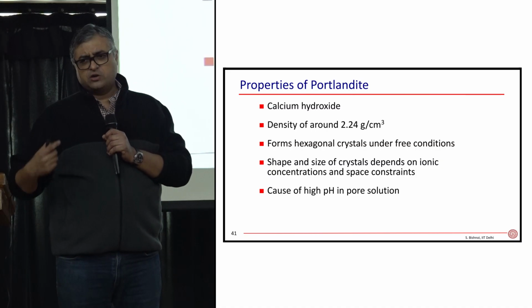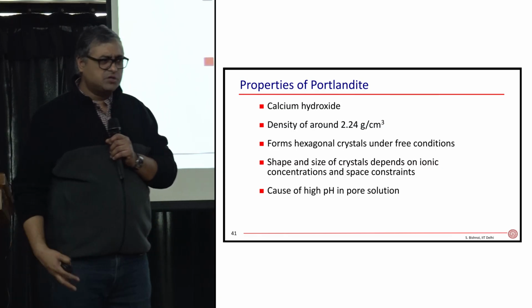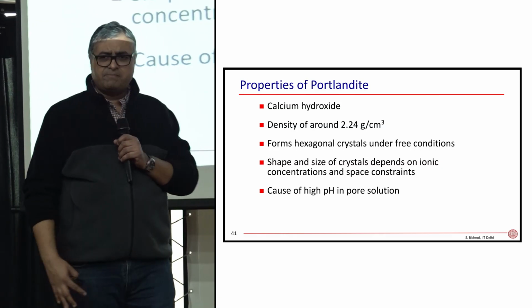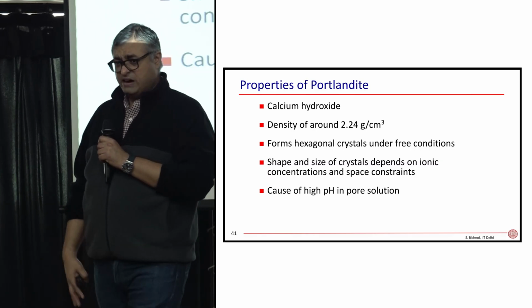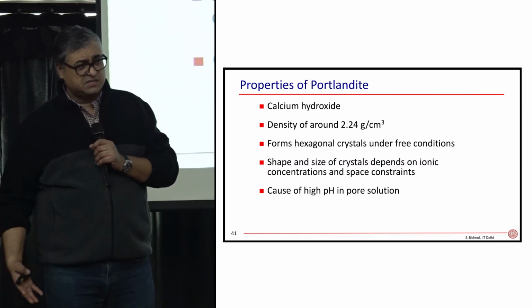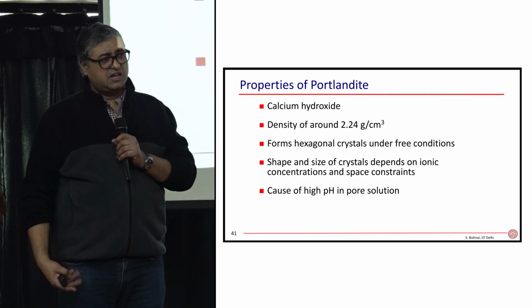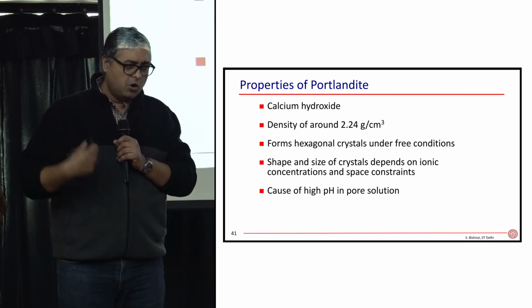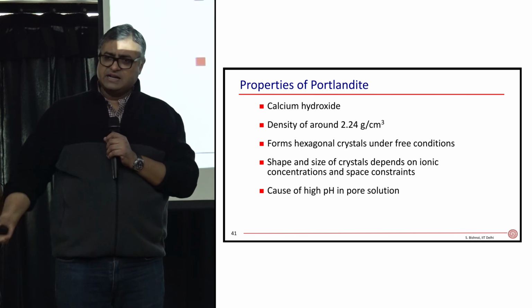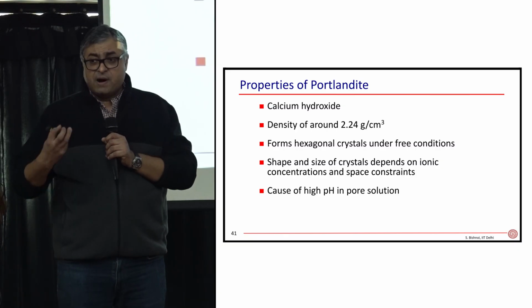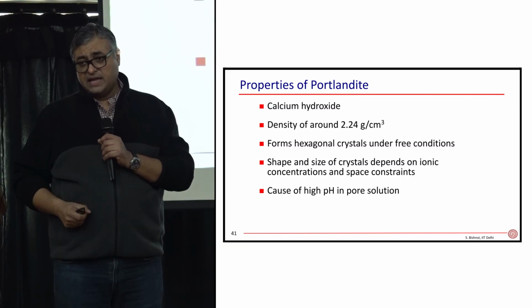People say that calcium hydroxide is a very bad product. I've read some books where people say that calcium hydroxide is a bad hydration product. It's not. It's a wonderful hydration product. It binds, it gives you strength, it's a good crystal, it has no porosity, no permeability, it doesn't allow anything to pass through it. It buffers the high alkalinity inside cements.